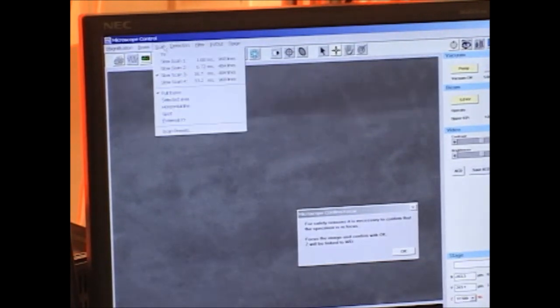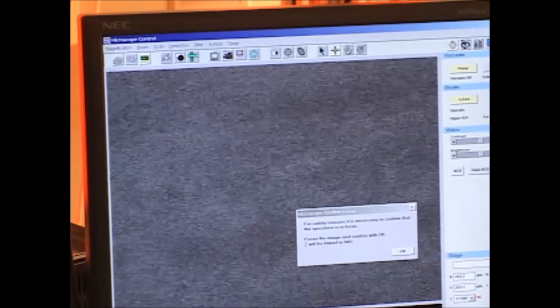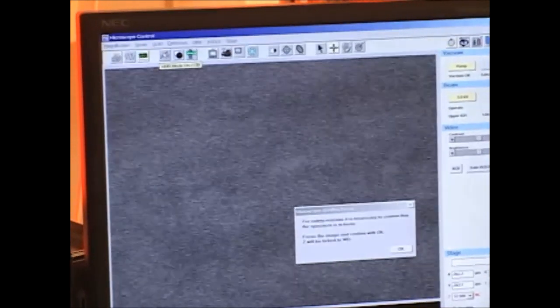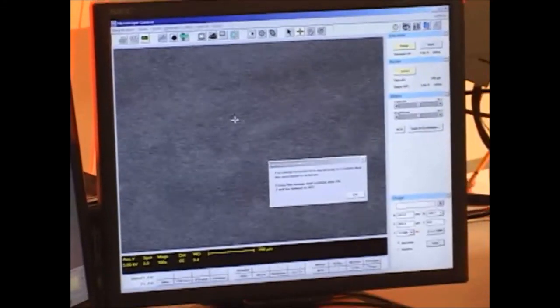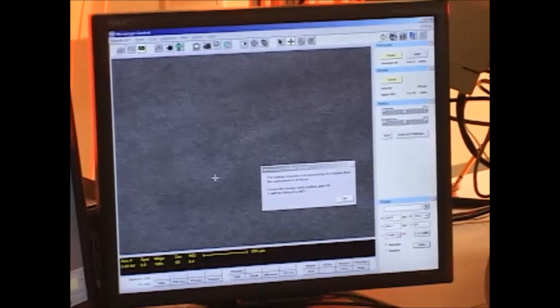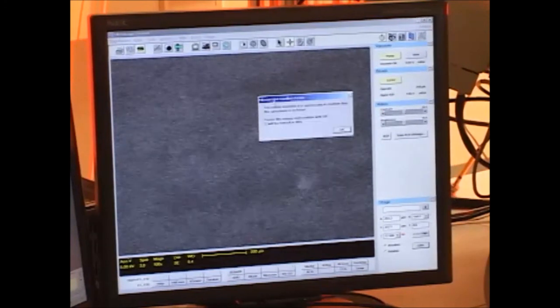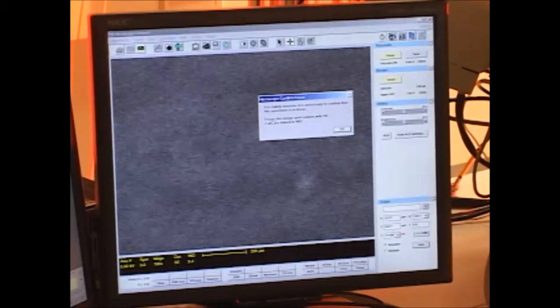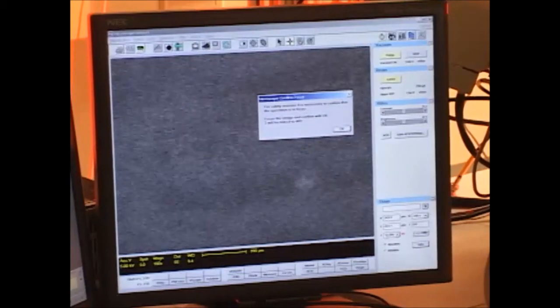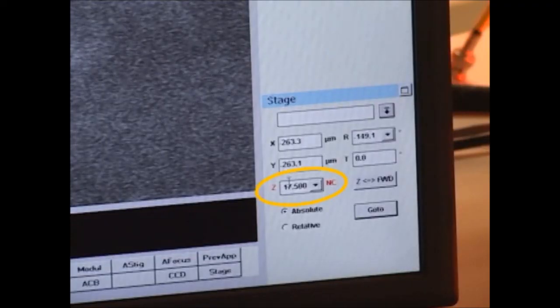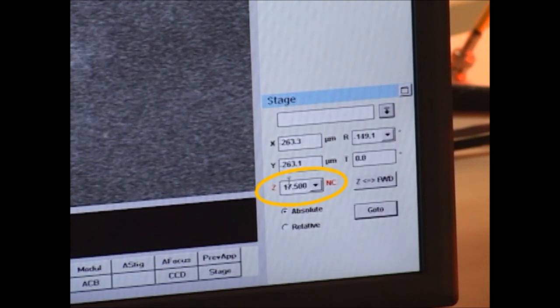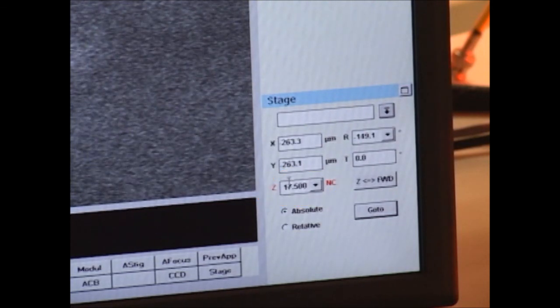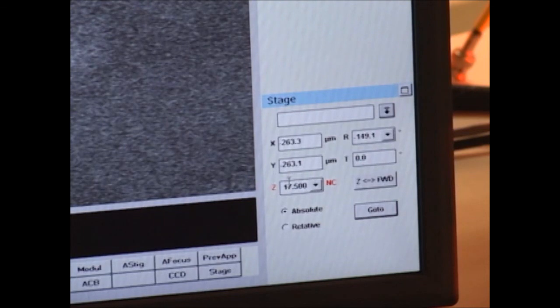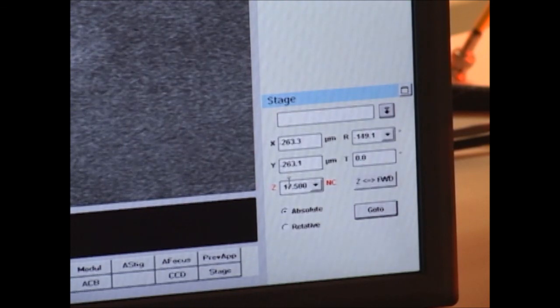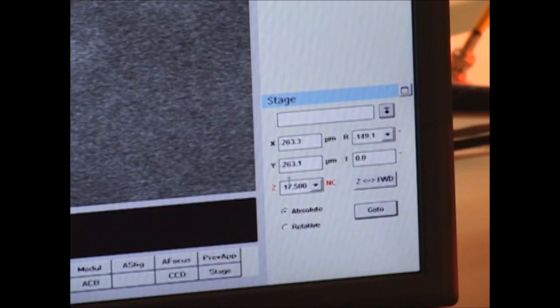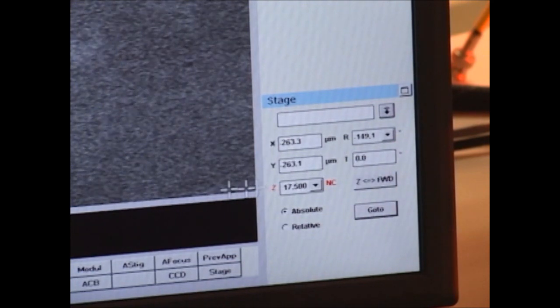So as long as we're moving the sample around and we want a live update, I'll leave the scan rate on TV. When we want to do fine focusing, we'll look at a slower scan rate that removes all of this noise from the picture. So I want to confirm that the microscope is in focus at 2000x so that I can tell the microscope how much clearance we have in the Z coordinate. Right now it reads Z not calibrated, and it's at a default value of 17.5 millimeters. This measurement is not a true measurement at all. When I get the sample in focus, this working distance will be a measurement in millimeters of the distance to the sample, the correct distance to the sample.